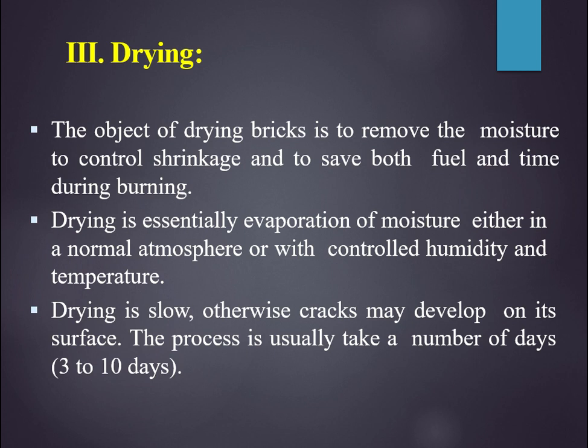The main objective of the drying step is to remove the moisture so as to control the shrinkage and also to save fuel and time during burning, right? If it is wet and has more moisture, you require more fuel to burn, but if it's already dried, you require less fuel to burn. Okay. One has to remember that the drying process should be a little bit slower. Why? Because if it is at a faster rate, you can likely have cracking due to internal shrinkage, right?